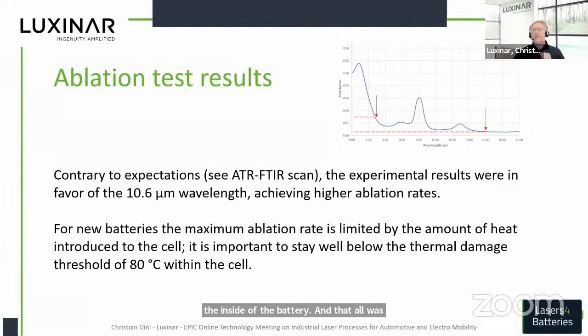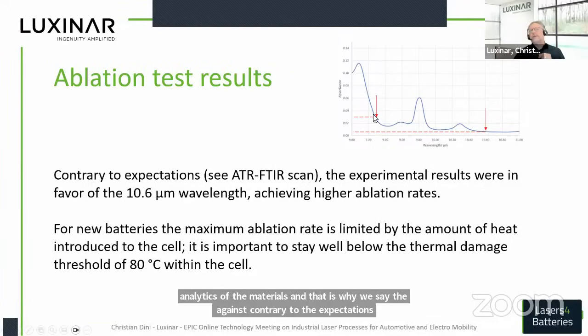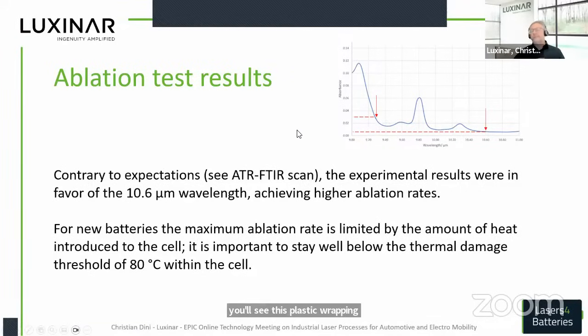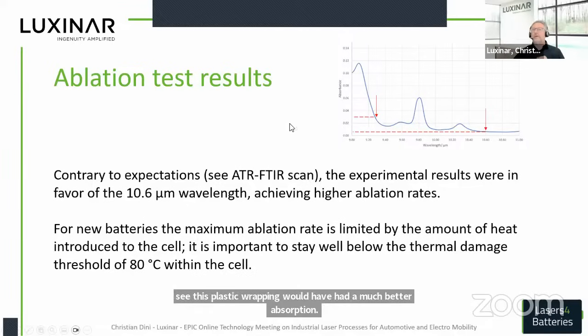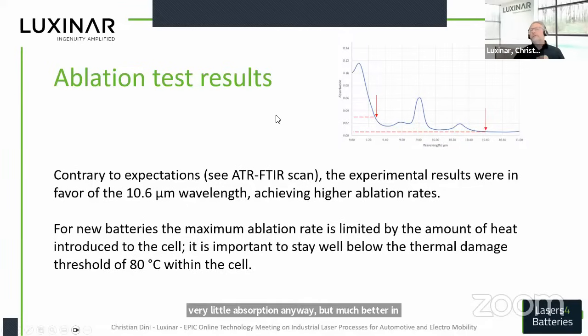We have a slide there. We always do spectrum analytics of the materials, and contrary to the expectations, you see this plastic wrapping would have had a much better absorption, though very little absorption anyway, at 9.3 than at 10.6. But in the end, that's always one of these surprises. The ablation rate of the 10.6 was simply more efficient and better, so we went with 10.6 here.